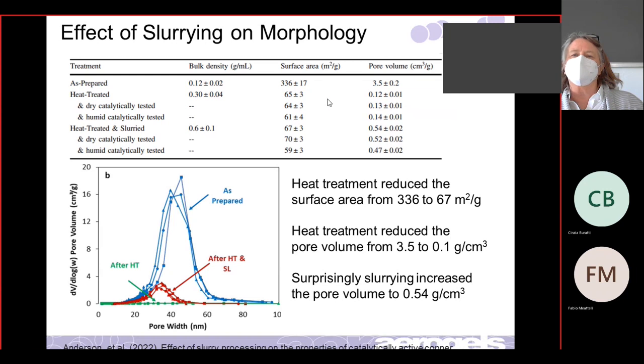The surface area drops. But you can see this initial one had a pore volume of 3.5 centimeters cubed per gram. Heat treated went down to 0.12. So heat treating, it all densifies. The pores collapse and everything. It's still an aerogel though, it still works. Heat treating also increases the density.